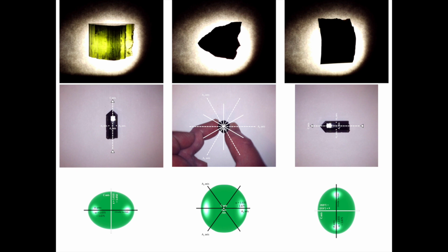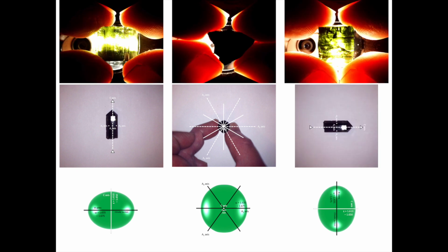The tourmaline examples today show us the usefulness of the polariscope. By using our plane polarized light when looking down the plane of the A-axis of our tourmaline, we can isolate light associated with refractive index epsilon and light associated with refractive index omega. This is in contrast to what occurs when we're looking at our tourmaline along the plane of the A-axis using normal light. There, no matter the orientation of our crystal, when viewing down the plane of the A-axis, we end up with the same result, where we have a blend of epsilon and omega. And we end up observing a deep green color.